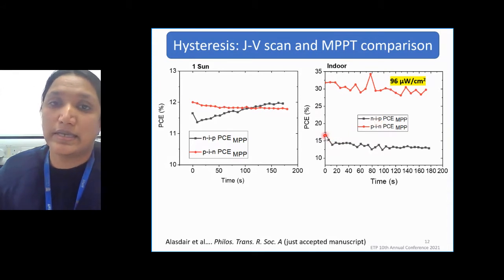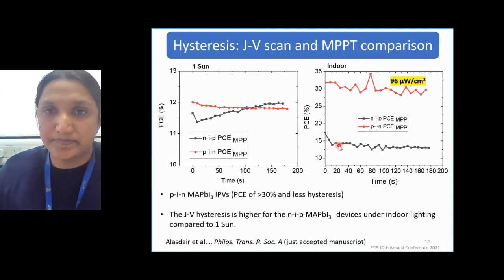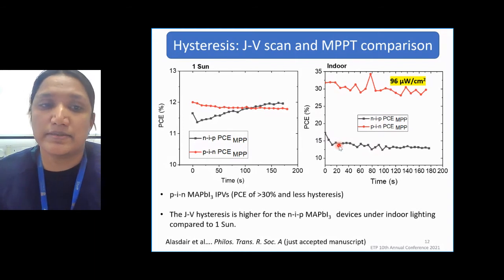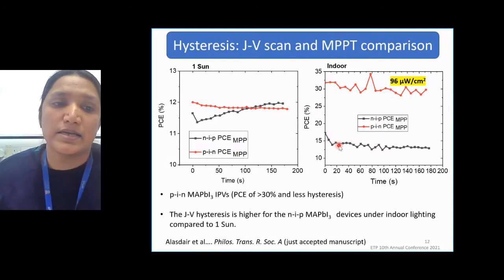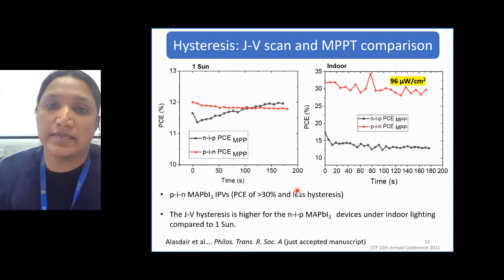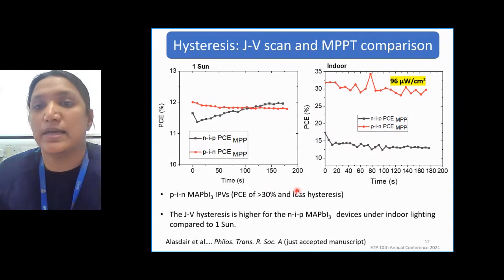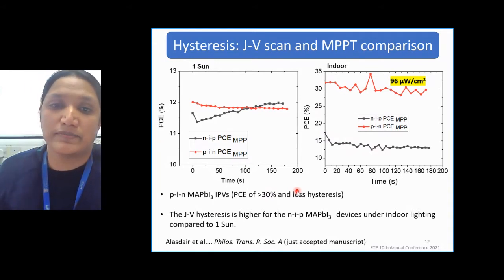So in deployable or under real conditions, these devices will only show less than 15% efficiency. From our comparison between the two device architectures, our study showed that, between the two structures we have selected, the PIN devices are more promising for indoor light harvesting and for powering the sensors because of their less hysteresis effect and their high power conversion efficiency.